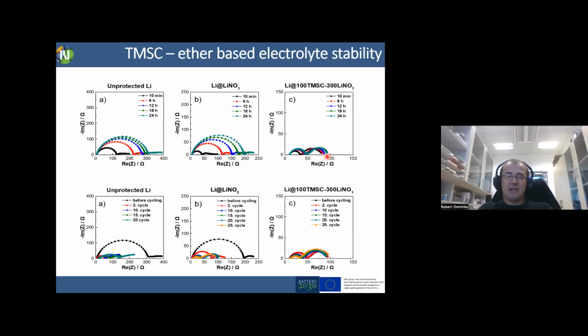And then also after cycling, this is even more pronounced. So this first semicircle, which corresponds to charge transfer, actually drops a lot because of the nanostructuring of the lithium, but we have another contribution because of the lithium diffusion through high surface area lithium and so on. While here you can see that it is pretty stable during the cycling. There is a small decrease of this first semicircle, again because of higher surface area available, but this second semicircle, which actually means diffusion, remains more or less constant.